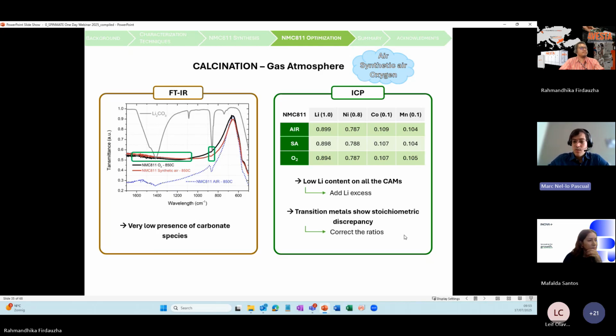Because what we thought was, if manganese and cobalt show a higher oxidation state than nickel, it is possible that, to compensate the electric charge of the material, you would need to compensate that by reducing the oxidation state of nickel. So increasing again the concentration of nickel 2+, so increasing the lithium nickel cation mixing. So in the end, if we assess this composition and we stick to the right ratio, we should have the minimum amount of lithium nickel cation mixing, and so a better performing material.